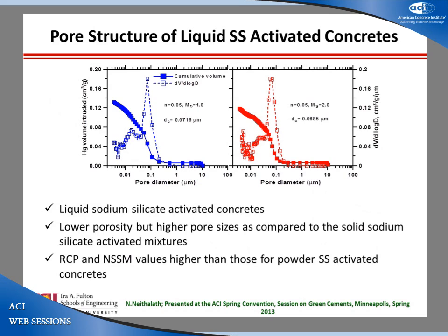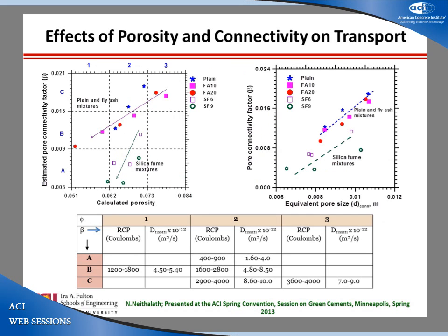But if you look at the liquid activated concretes, you can see that the porosities are much lower. We talked about 16%, and now you're at about 12% porosity, but the pore sizes are much higher. So lower porosity but higher pore sizes here, and these two have implications on how transport happens.